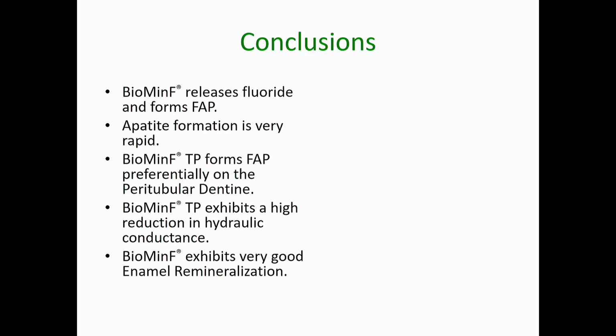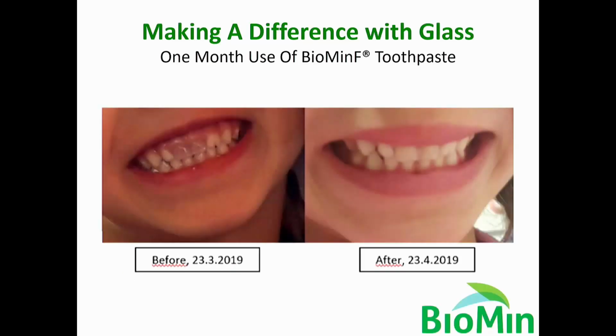So the Biomin F toothpaste releases fluoride, it forms fluorapatite. The apatite formation process is very rapid. It forms the apatite preferentially on the peritubular dentine, and it exhibits a very high reduction in hydraulic conductance, and it's extremely good in terms of enamel remineralization rates.